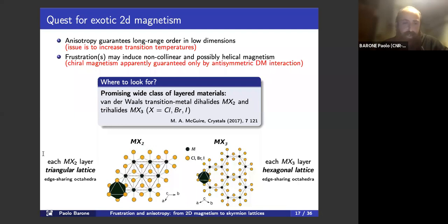So I'm showing here the two typical structures of an individual layer of the van der Waals system. In the case of trihalides, we have seen that we have this hexagonal lattice, which is formed by transition metal in an octahedral environment with edge-sharing octahedra. The dihalides case is pretty similar. The only difference is that we are filling the hole of this hexagonal lattice and obtaining a triangular lattice. But for the rest, they also are formed by edge-sharing octahedra within each layer.